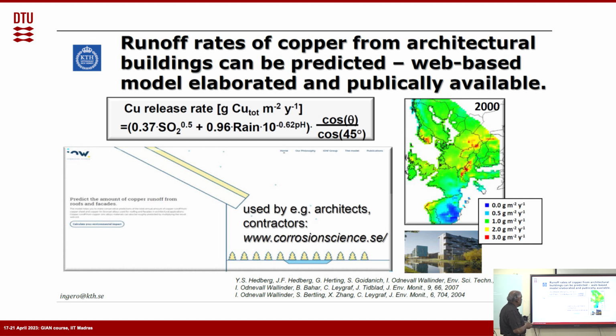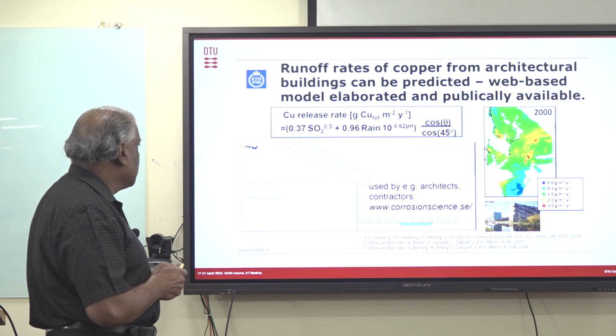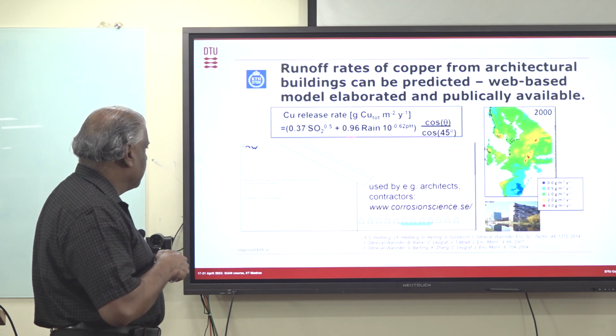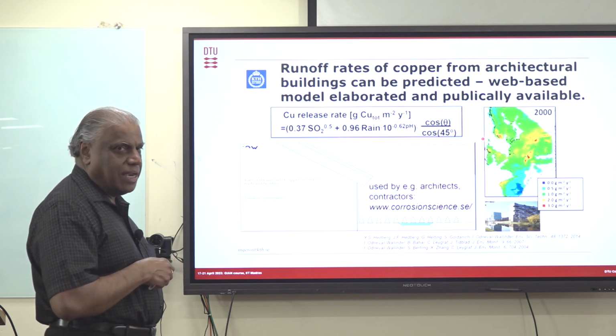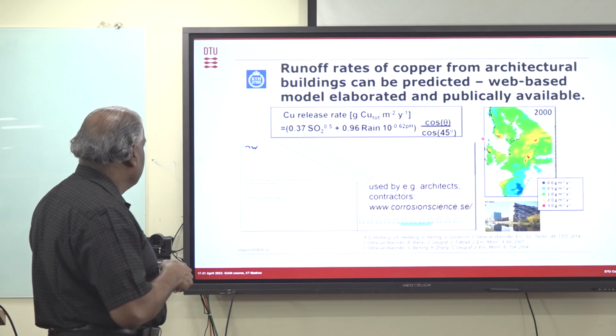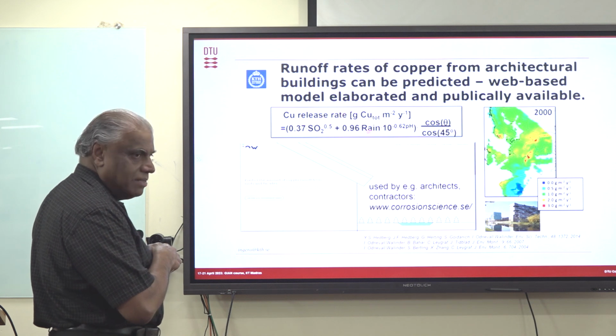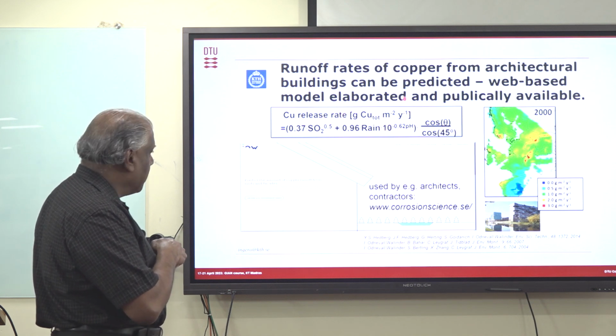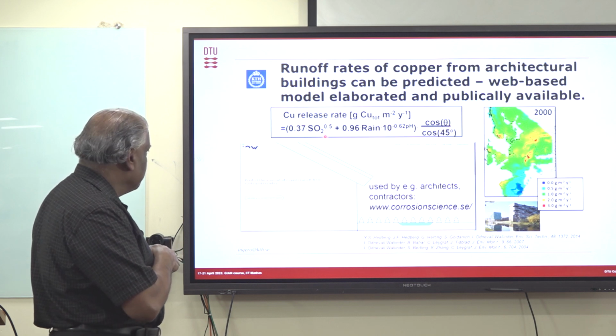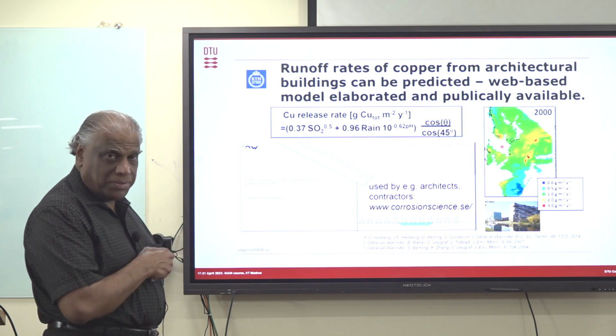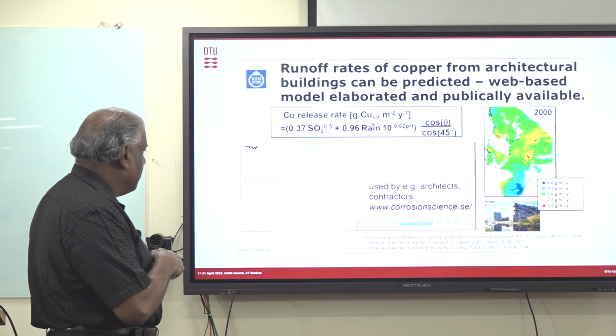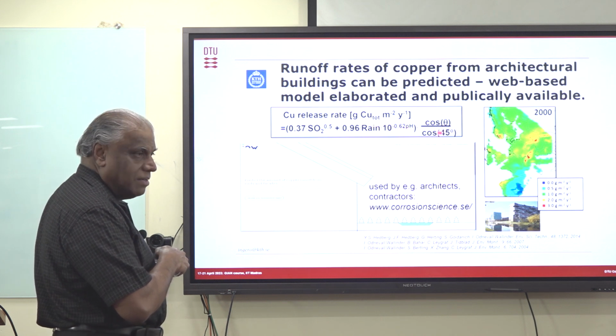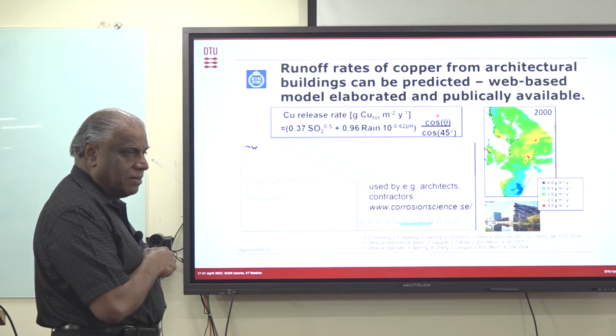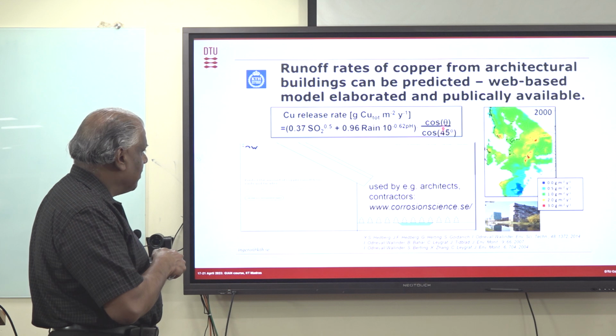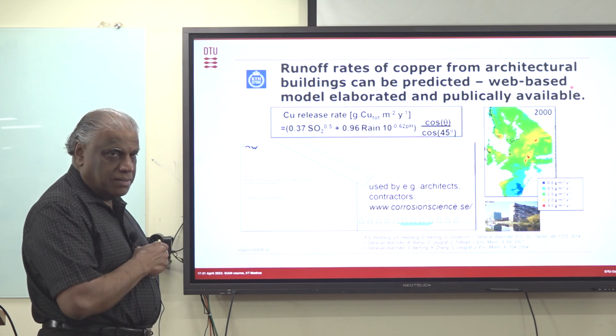So they actually came up with an equation. It's not a perfect equation, but you can calculate the copper release if you know many of these factors. This is coming from their work, collecting a lot of data from Europe at different places. If you look here, you can see the copper release rate per square meter per year of the roofing is a function of the SO2 content in the atmosphere and rain. As far as rain is concerned, the pH is the most important thing. So there is a 10 to the power of this pH term, and also cos theta divided by cos 45, that is the angle of exposure, as well.